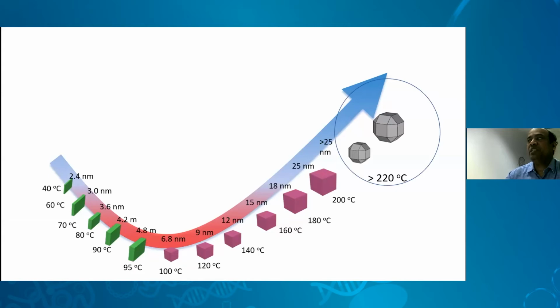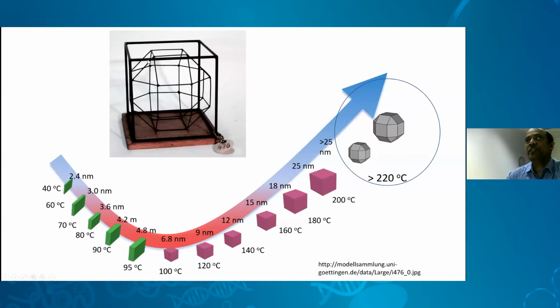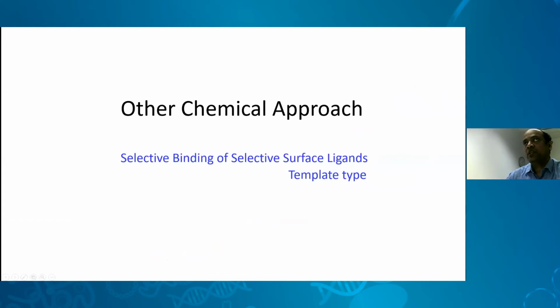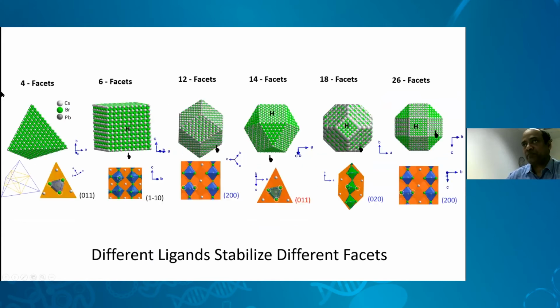So basically, how are these new facets coming out? If we look at it, I go back to this model. It shows a cube where the corners have been cut, the sides have been cut, the edges are cut. If we cut down from a cube, we can get this type of structure. So that's one method. The other method is the selective binding of selective ligands on the surfaces, which behaves like a template. It can also give facet-selective polyhedra.